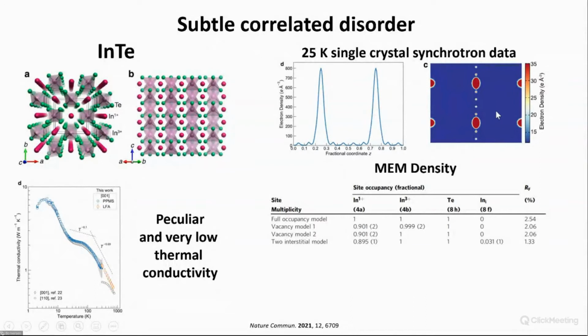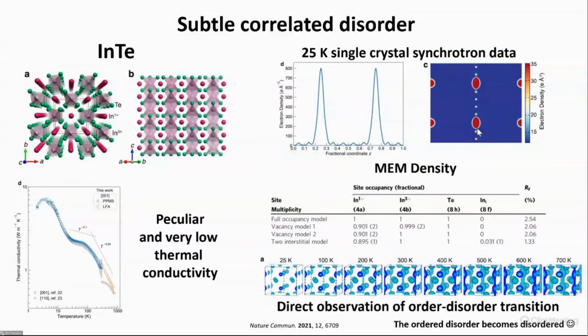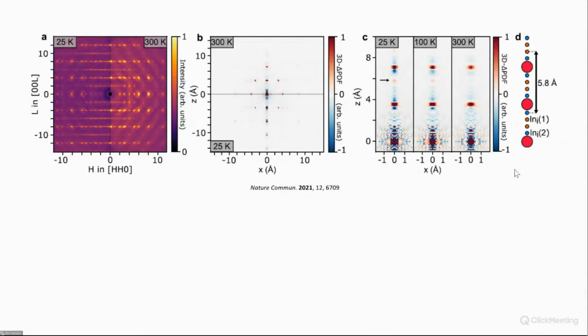Now, if we add these into our normal structural refinement, we can see that we can get the R value to drop to about 1/2. So clearly the data like this disordered model, and it also shows that both the main site and these secondary sites are very disordered, and this of course affects the thermal conductivity. We did measure the single crystal data up in temperature, and we see this really wonderful transition from having separate sites of the disorder to basically getting this sausage through the structure. So what you see is this order-disorder transition as you heat up the sample, and then indium 1+ can zoom through these channels.